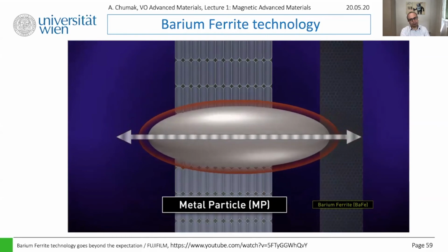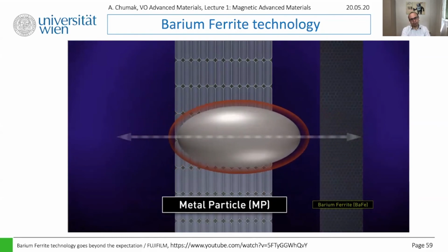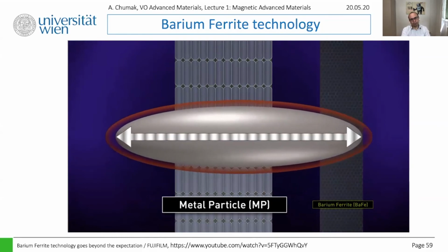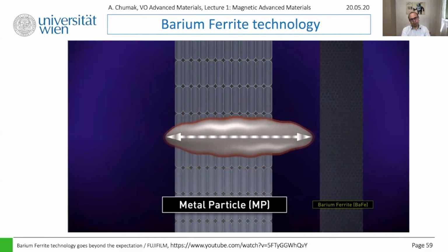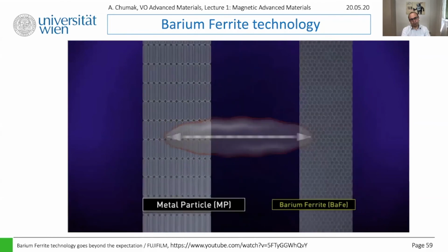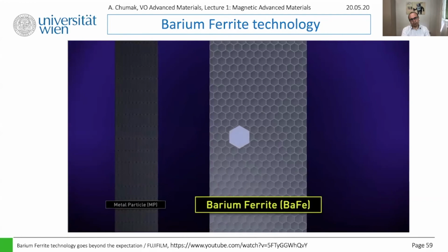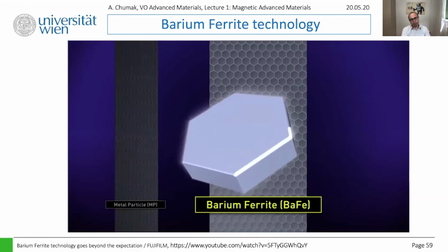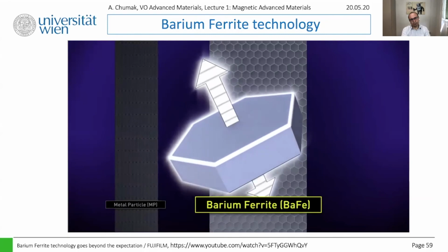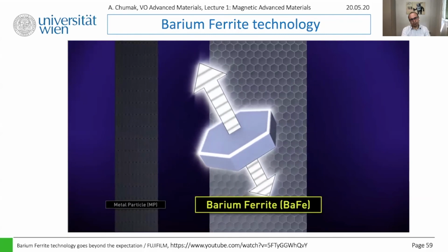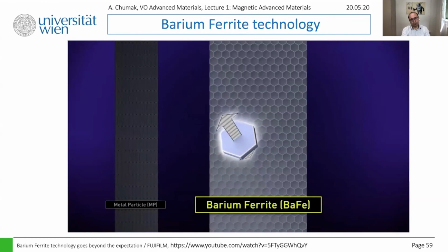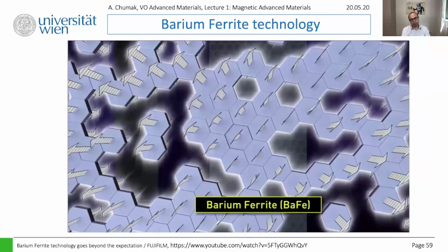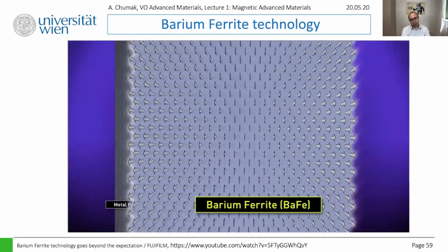But changing their shape to achieve miniaturization weakens their polarity, destabilizing their ability to store information. Miniaturizing them while retaining their shape also results in chemical instability caused by the thinning of the antioxidant layer. On the other hand, the magnetism of barium ferrite relies on its hexagonal crystalline structure. This means that miniaturization does not lower its magnetism. Moreover, barium ferrite is already oxidized, so it does not require an antioxidant layer, enabling further miniaturization.